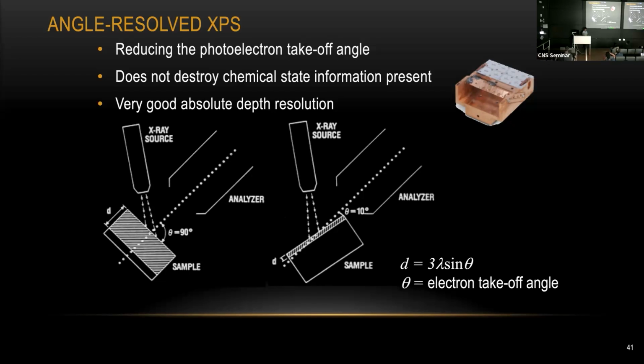For instance, if you're doing some kind of monolayer self-assembly coating on the surface, your coating is only about 1 angstrom, 2 angstrom, and you want to pick up most of the signal from your coating, not from your substrate. In that case, you can do some tilting. By tilting, you're changing your take-off angle, so you can reduce your sampling depth. Here is a very simple formula about how we can change the sampling depth from 10 nanometers down to maybe just 2 or 3 nanometers. So that's the whole idea of angle resolved XPS measurement, which means you just want to get signal mostly from your top region only.